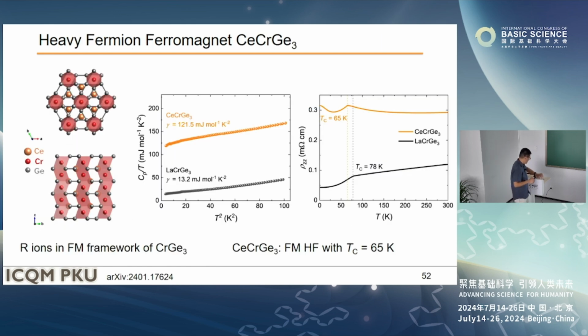Okay, we also have some other examples. We were just trying to look around to see whether we have some ferromagnetic Kondo lattice, and we picked up the crystal and did some measurements, asking the student to do that. Fortunately, we found another example. This is cerium chromium germanium 3. Here, the chromium also has some magnetic moment. And you see the lanthanum and cerium compounds both have a TC around 80 Kelvin. And the cerium compound has a clear log T behavior, meaning its Kondo effect plays an important role.